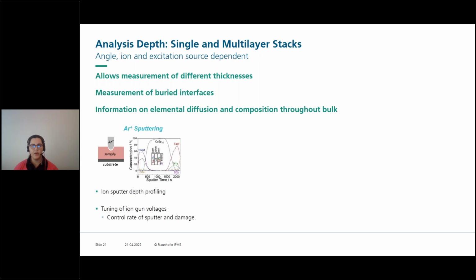One way we can do this is using argon ion sputtering. You see a nice sketch here where you have a sample film on the substrate and you simply use argon ions to bombard your sample surface. In the plot here, you see sputter time on the x-axis versus concentration of your elements on the y-axis. For example, you have 3 different layers here with different composition: the first layer with ruthenium, the second layer with cobalt, and the third layer with tantalum. And using argon ion sputtering, you can obtain a depth profile.